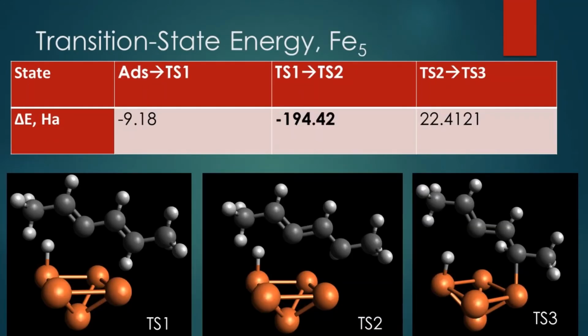For the iron 5 surface, there is about a 9 Hartree drop in energy upon hydrogen abstraction, but then an almost 200 Hartree drop upon entering TS2. What's more, there is a 22 Hartree barrier to TS3, indicating that iron 5 prefers to move the carbon radical but not to react with it further. This opens up the possibility of the carbon radical beginning polymerization, which would mean the iron surface could initiate the seasoning process from the bottom up.